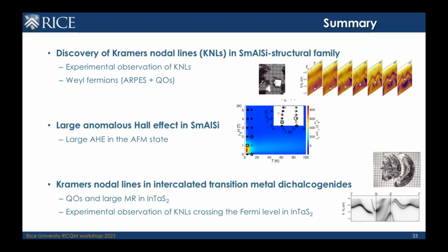I know that Colin has done neutron measurements on this. I think one of the problems they had was that there was some aluminum silicon site mixing, in addition to the fact that this is incommensurate. Depending on how much site mixing you have, the structure actually changes from non-centrosymmetric to centrosymmetric, so I don't know that they were convinced that their structure remained.